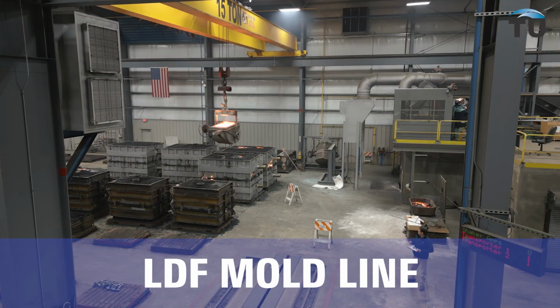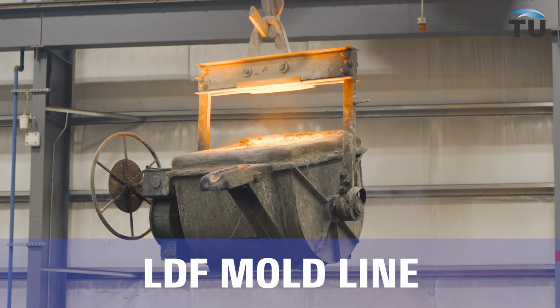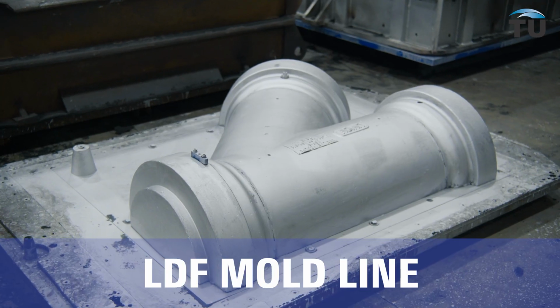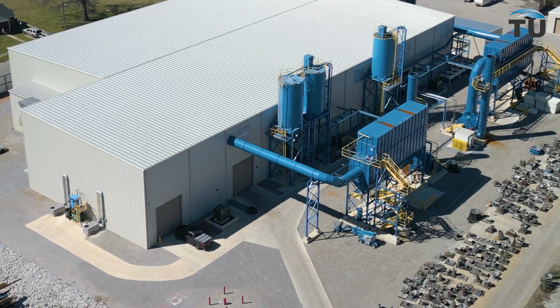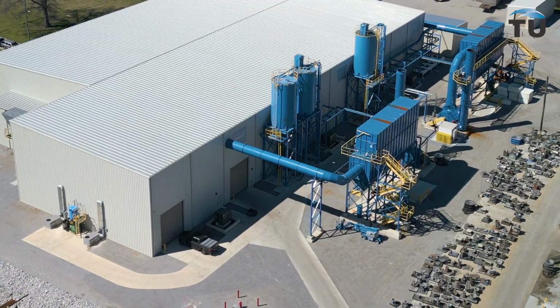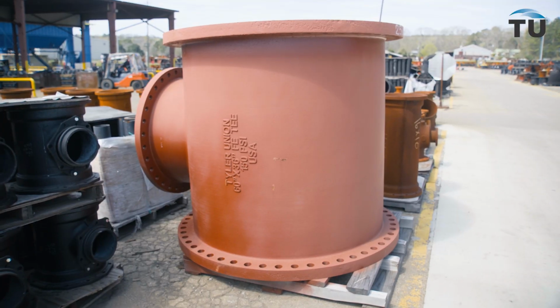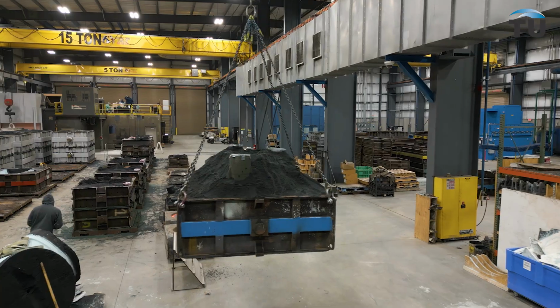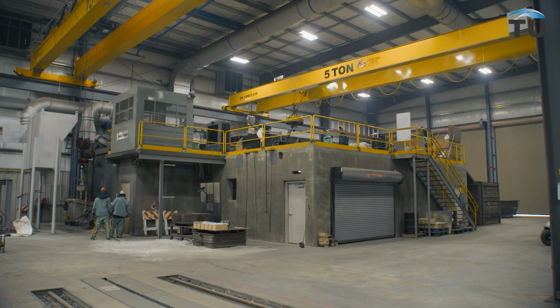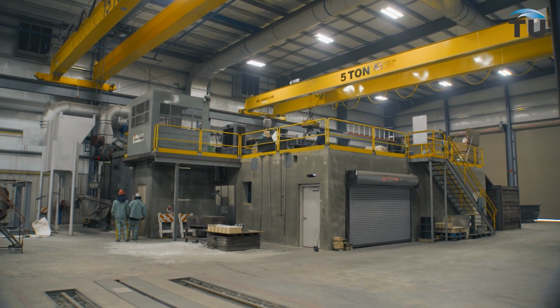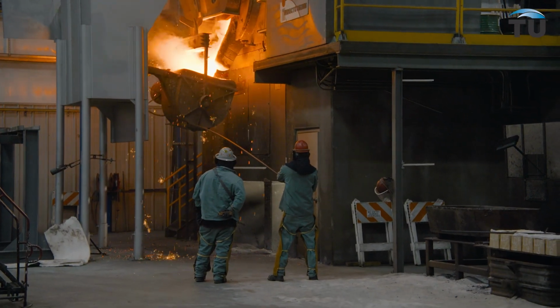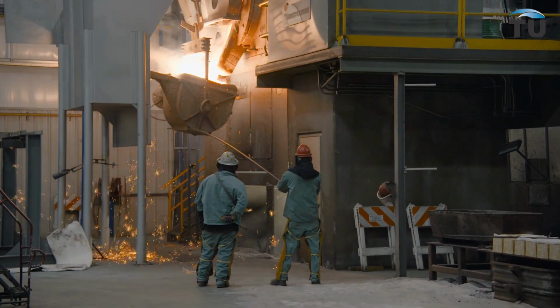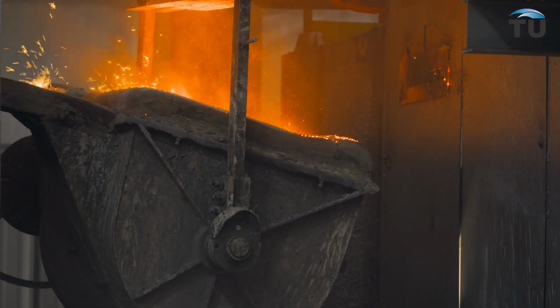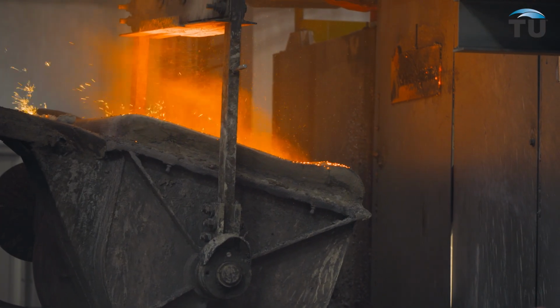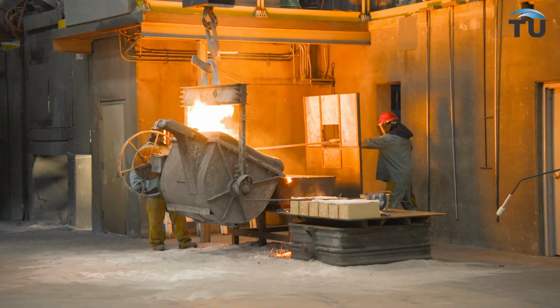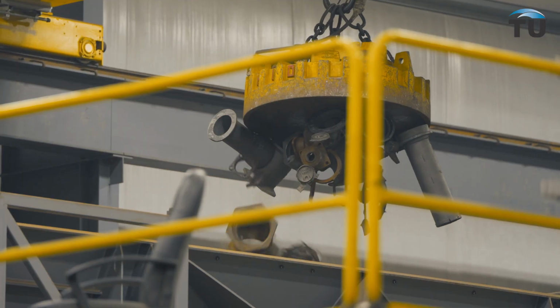The second no-bake molding line is Tyler Union's large diameter Foundry, or LDF, a 53,000 square foot facility producing some of the company's largest diameter products. Castings in the LDF are produced using an induction melt furnace rather than cupola. This energy-efficient melting process uses a water-cooled copper coil with alternating current to induce a magnetic field around the charge to be melted. This creates resistance, and energy is dissipated as heat to melt the recycled scrap.